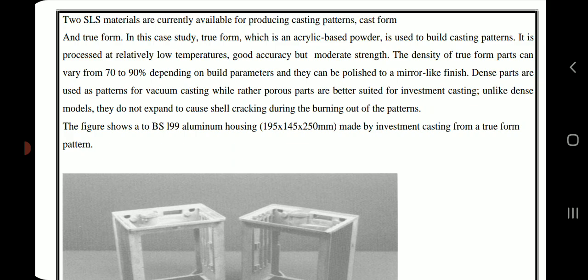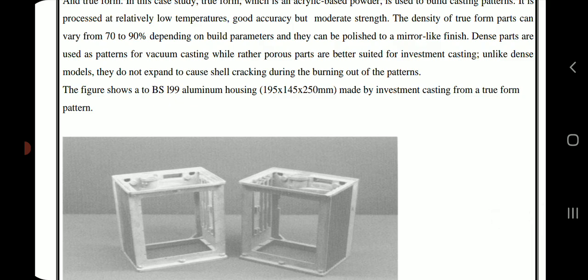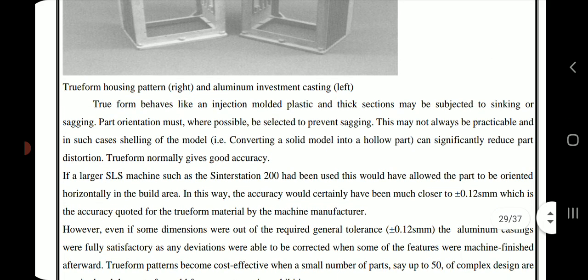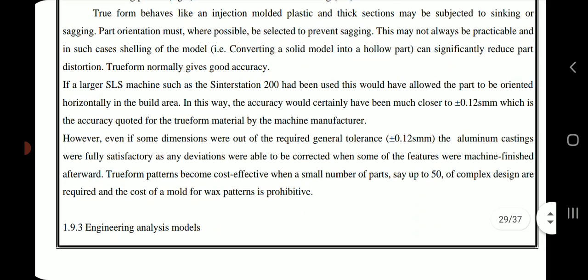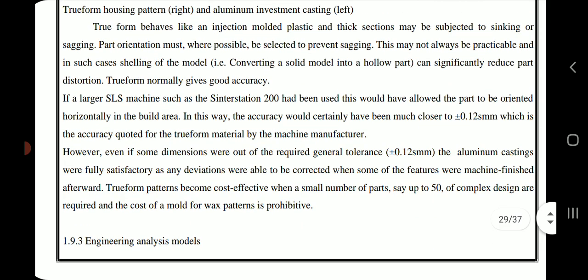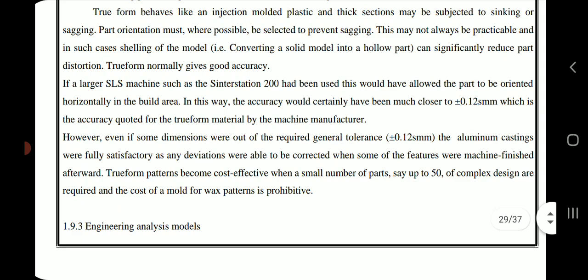Dense parts are used as patterns for vacuum casting, while rather porous parts are better suited for investment casting. Unlike dense models, they do not expand to cause shell cracking during the burning out of the patterns. The figure shows a BS-199 aluminum casting made by investment casting from a TrueForm pattern. TrueForm behaves like an injection molded plastic, and thick sections may be subjected to sinking or sagging.